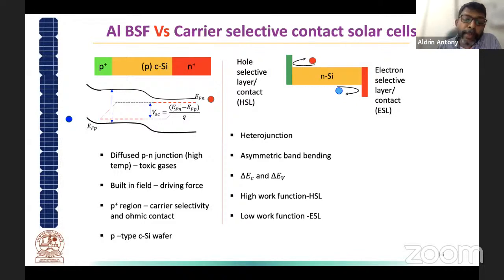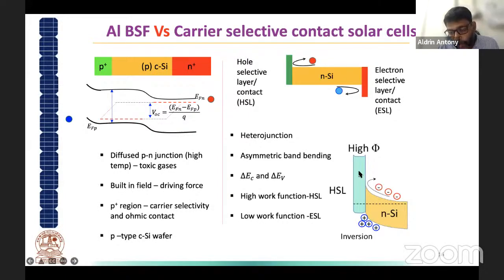And if you look into the type of materials which are used for HSL and ESL, high work function materials are used normally for the HSL, and low work function materials are used for electron selective contacts. So this is how a high work function metal works. When the two materials are joined together and the Fermi levels get aligned, a huge band bending occurs in the silicon, which prevents the electrons from moving in this direction. So a band offset forms at this silicon HSL interface, and it blocks the electrons and can only pass holes in this direction. And an inversion layer is formed, and from here electrons can move into this layer through the contacts by tunneling or thermionic emission.